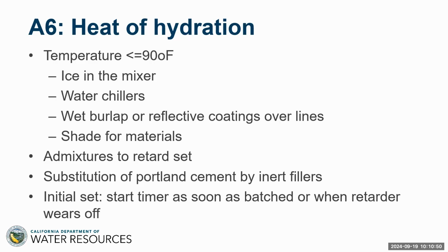We can also use admixtures, as we said, as retarders, and this will help prevent cracking because the grout can hydrate without other things happening. We can substitute Portland cement by inert fillers, for example, sand, limestone. Many of you know now that we're dealing with type 1L cement as opposed to type 1-2. And the 1L has a substitution of limestone for cement, so that reduces the heat of hydration. For big bulk infill jobs that we used to do in the old days, we may have had something like an 8-to-1 ratio between fly ash and cement. We don't typically want to talk about fly ash too much anymore, one of the main reasons being that it's becoming scarce because nobody is burning coal anymore. So we're kind of de-emphasizing the potential for ash.